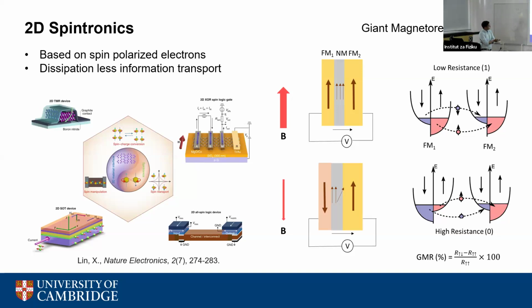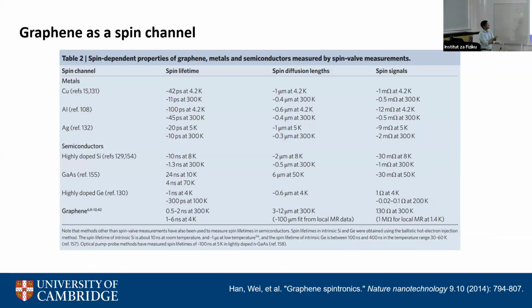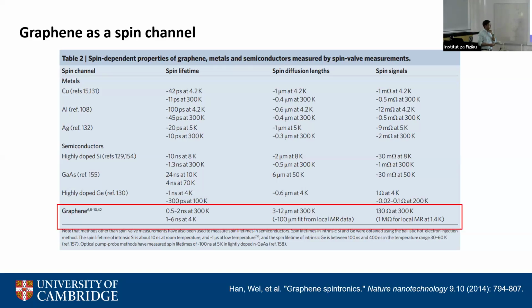And we wanted to work with graphene because graphene is a very good medium. If you want a spintronic device, you want a material which can carry spins, because that will be your spin channel instead of a charge channel. Copper, aluminum, silver, all of these materials were being used for spin channels. But in 2007, Professor Bart van Wees's group in Groningen showed that you can really use graphene for very good spin conduction, because graphene has very long spin lifetimes and a very long spin diffusion length. And this stems from the fact that graphene has very low spin orbit coupling. It is made of carbon, and you cannot really flip the spins in graphene very easily.